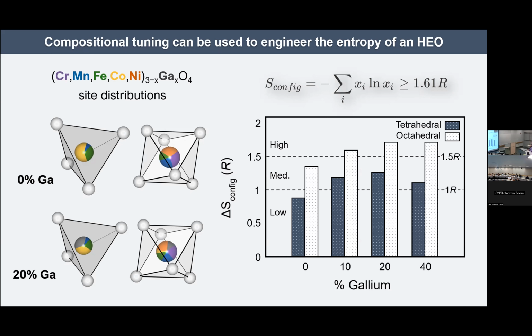Right. So for say the 0% sample, I'm treating this one separately first and then doing this one. So that's what the 2 bars represent. And here I have roughly, say, 0.6 is cobalt. So then my first species is 0.6 ln 0.6. And then I have maybe 10% of manganese, and so that's 0.1 ln of 0.1. So you add up all the contributions. So it does assume nothing about the geometry. Yeah, the geometry is not important.